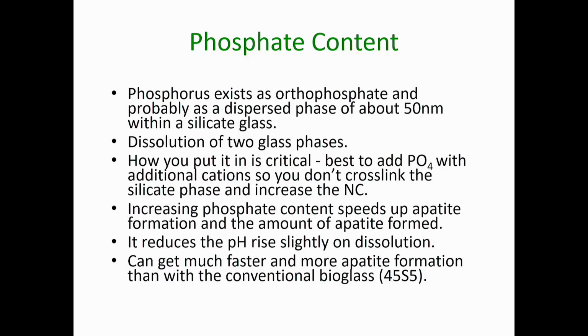The phosphorus content in the glass, or phosphate content, is also important. The phosphorus in the bioactive glass exists as orthophosphate, the same form that's present in the apatite. And it probably exists as a dispersed phase of about 50 nanometers contained within the silicate glass. So we may have in bioglasses the dissolution of 2 glass phases. It's important to design the glass so that when you put the phosphate in, you don't cross-link up the silicate phase of the glass and increase the network connectivity.